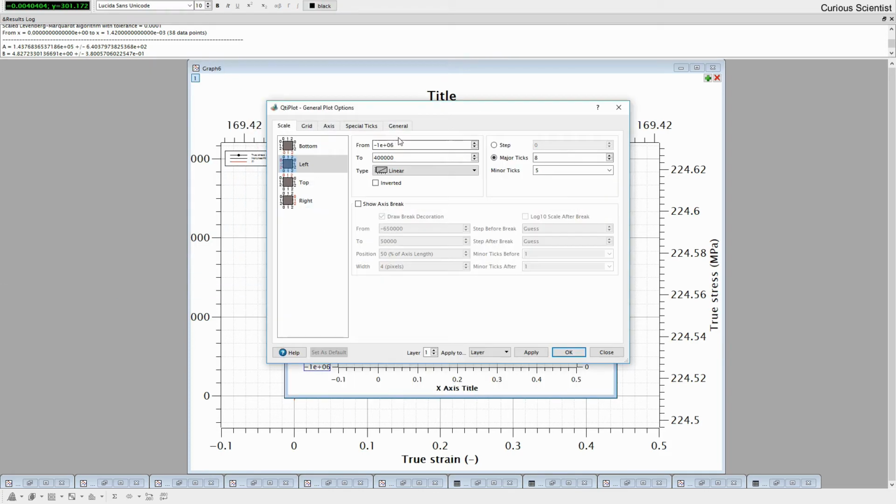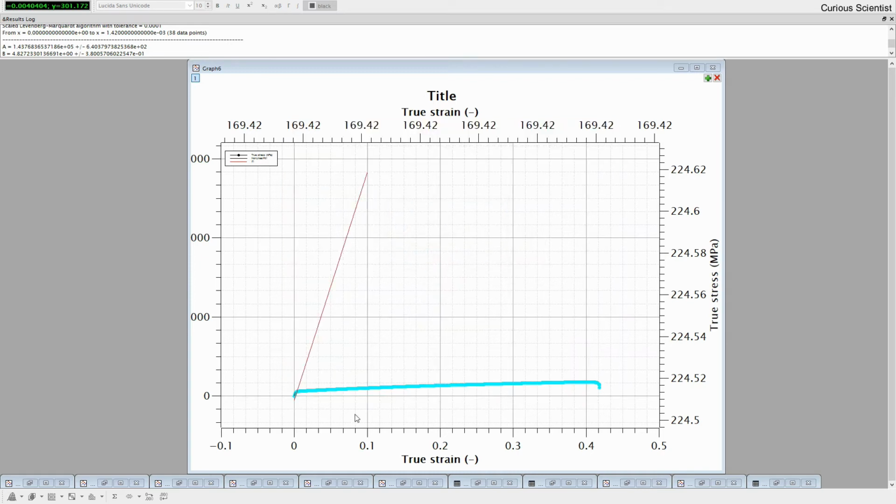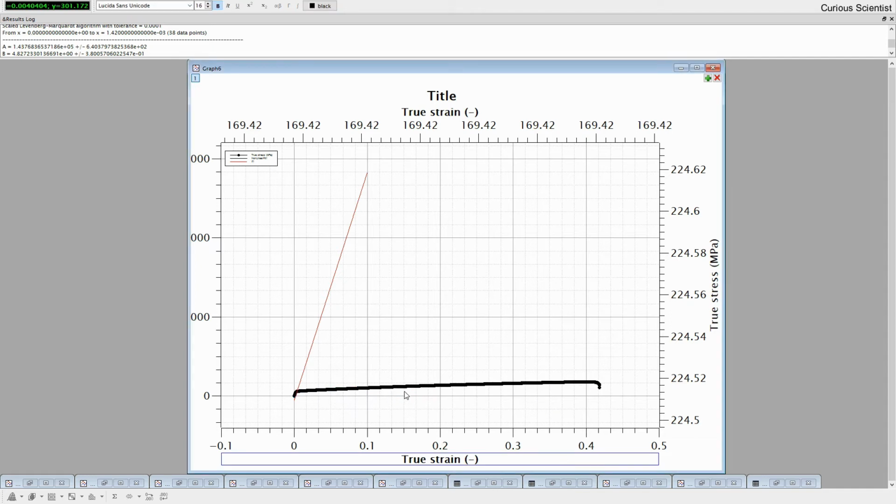So once you can see, because the points are scattered within a small region, but there is a lot of scattering, so the derivative will go crazy and you cannot really get any useful values from this. So, which I usually do, I discard some values and I just try to reduce the number of points along this curve to 100 or 200. That's fine.